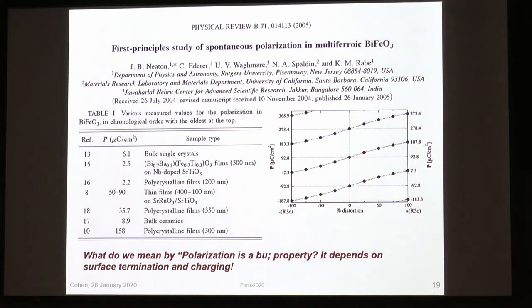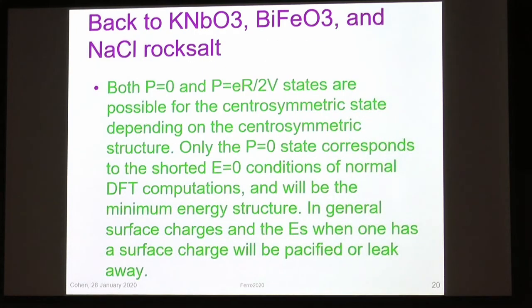So what do we mean by polarization being a bulk property if it depends on surface termination and charging? I think that this is something I'll leave to the discussion period. But I went and looked at this system again, and I find indeed that I can make a zero polarization case, not the half a quantum, for bismuth ferrite that's centrosymmetric, that's a perfectly good reference state too. So it seems like you can get both results, both the zero result and the half a quantum result, in a DFT calculation. So back to potassium niobate, bismuth ferrite, and sodium chloride, and I'll finish up.